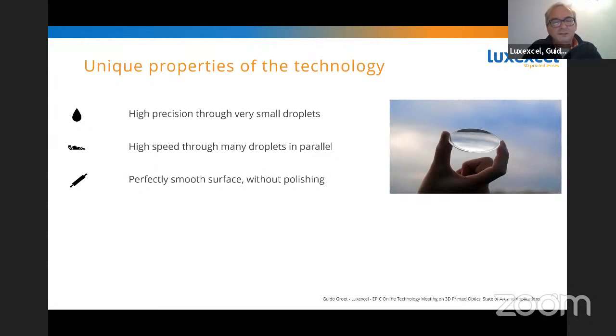The other thing that's great about the technology is that because we use droplets, we let them flow. You can imagine that they become perfectly smooth. So we achieve a surface roughness in the 5 nanometer range. So it's very smooth without any polishing, which is a great benefit, not only because it simplifies things, but also because it doesn't damage, for example, a smart device that you integrate into a lens, because there's no force applied. And also because we do this at close to room temperature, there's also no stress applied to the lens, and so it's a very usable lens straight out of the printer.